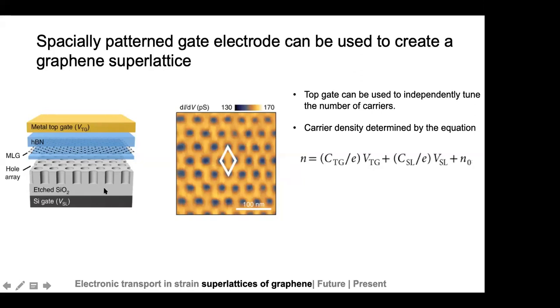a backgated device. So you can essentially apply an electrostatic potential in graphene, which will have this sort of a triangular lattice structure, and thus generate some superlattice effects. They also have a separate metal gate on top, which gives you an independent control over the number of carriers. And so the total carrier density is going to be a combination of both the top gate voltage and this backgate voltage, which we are calling the superlattice potential.